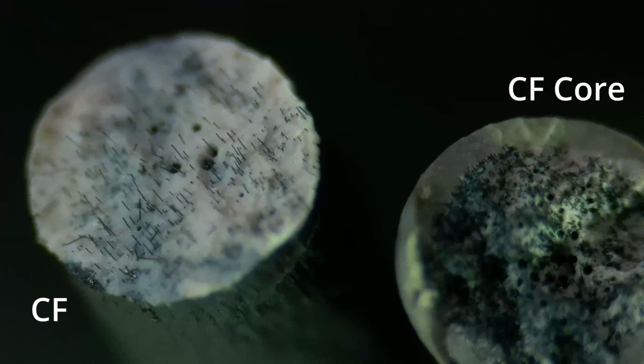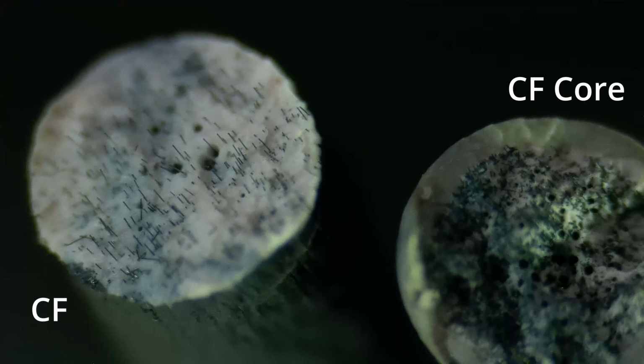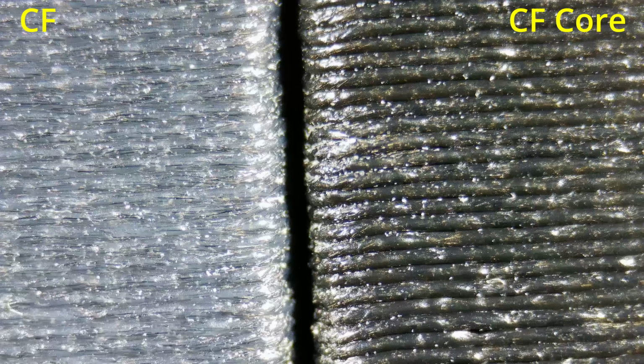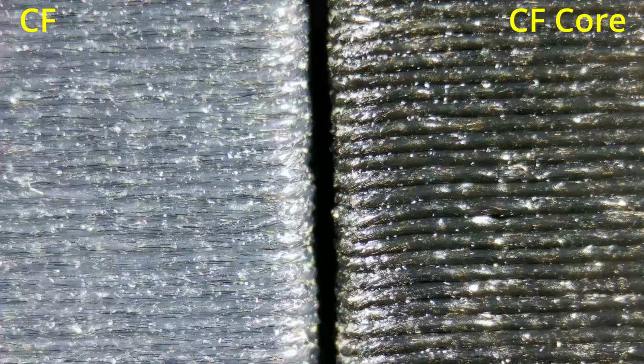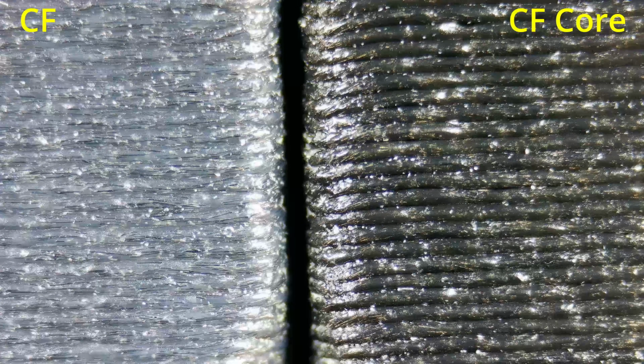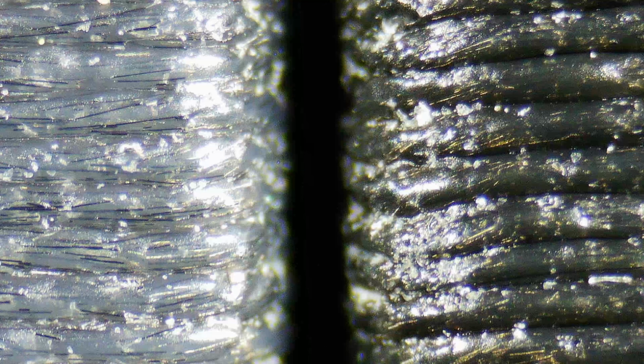On the left side you can see the regular carbon fiber, and on the right side we can see that core skin which doesn't have the fibers on the edge of the filament. And we can see high density of the fibers inside. And this is the printed object under the microscope, and we can clearly see those fibers on the left side, but they're not exposed, they are melted into plastic. But the core version on the right side is quite smooth.